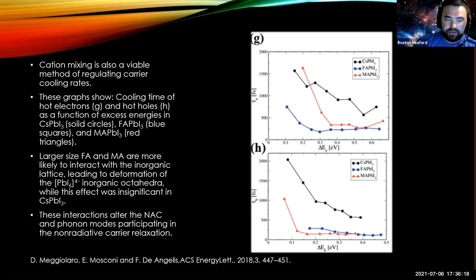And so it was found that the larger size cations are more likely to interact with the inorganic lattice, which leads to deformation in the octahedra, but in the cesium perovskite, this was insignificant. And these interactions will change the nonadiabatic coupling and the phonon modes that are participating in the non-radiative relaxation. That's another thing that can significantly affect how efficient your systems are.